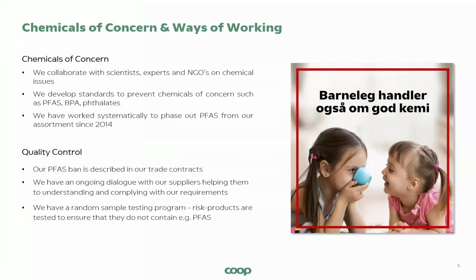When it comes to chemicals of concern, we collaborate with scientists, experts, and NGOs on chemical issues. And we have been developing standards to prevent chemicals of concern, such as PFAS, BPA, and phthalates. And we have also worked systematically to phase out PFAS from our assortment since 2014. And of course, it also requires a lot of quality control when we are ahead of legislation. So just to specify, our PFAS ban is described in our trade contracts. We have an ongoing dialogue with our suppliers, and we're helping them to understand and comply with our special requirements. And then we also have a random sample test program where we make sure that risk products are tested to ensure that they do not contain PFAS.